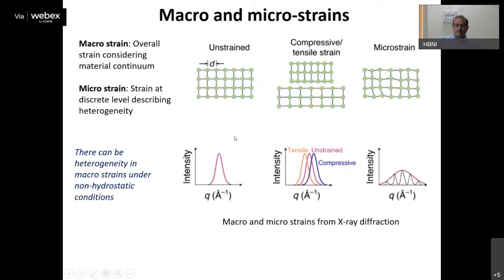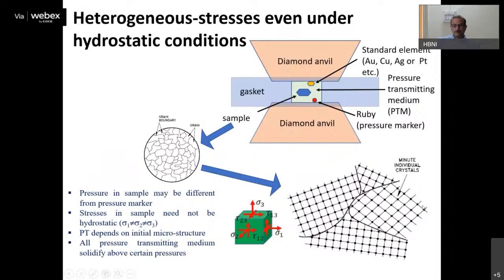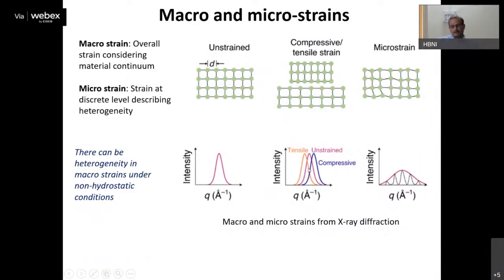Many a time in non-hydrostatic conditions, there are even macro strain heterogeneities. So within our cell, it may not necessarily be an equal stress state all over the cell. There can be macro stress heterogeneities. So sometimes if your probe size, like the size of your X-ray beam, is large enough that it cannot distinguish these macro strain heterogeneities, you can confuse them with micro strains. That's why it is very important to select the proper size of the beam depending on the heterogeneities within the sample that you want to probe.